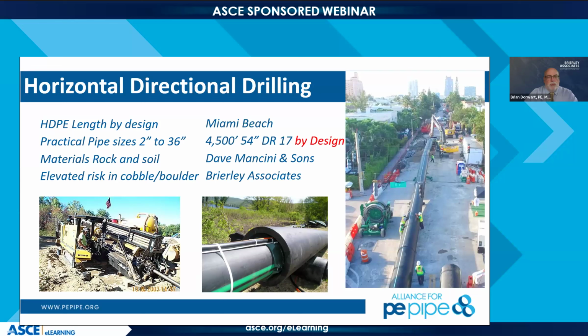The nice thing about the HDPE, we're going through granular material, really nasty, cobbly boulder. The only material that we really determined was going to be tough enough was HDPE. That kind of material can break PVC, and it'll gouge any surface and corrosion protection you have on steel. HDPE is the ideal component. We fused it all together and pulled it back in one shot in about 3 hours. It shows that in bad conditions, toughness really does make a difference.